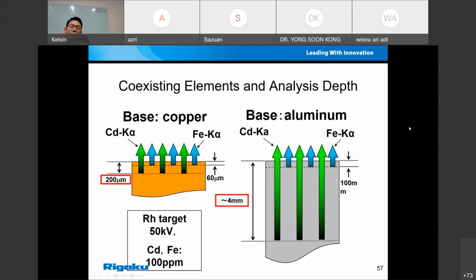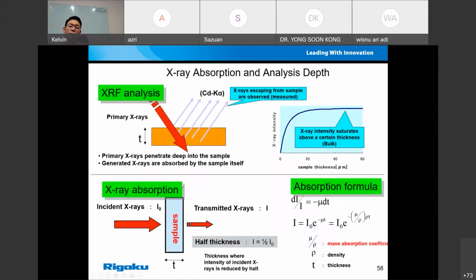And also the thickness that the X-ray can penetrate depends on the material. Generally speaking, we say the light elements allow the X-ray to penetrate deepest, so the penetration depth is higher. Where you have a high Z medium, the penetration depth is going to be very, very small.